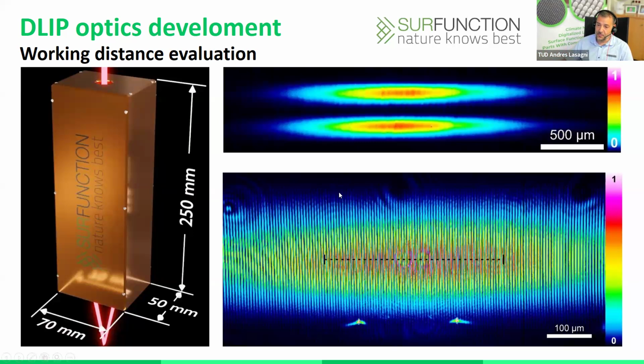So as you can see here in the picture, we have very elongated spots. And within these spots, I can imagine you see all these lines. This is called an interference pattern. So we have a periodic variation of the laser energy. And what you see now with colors are the positions over the surface of our material where we are bringing energy. That means we can ablate, we can remove, we can evaporate or melt the material just at this position.